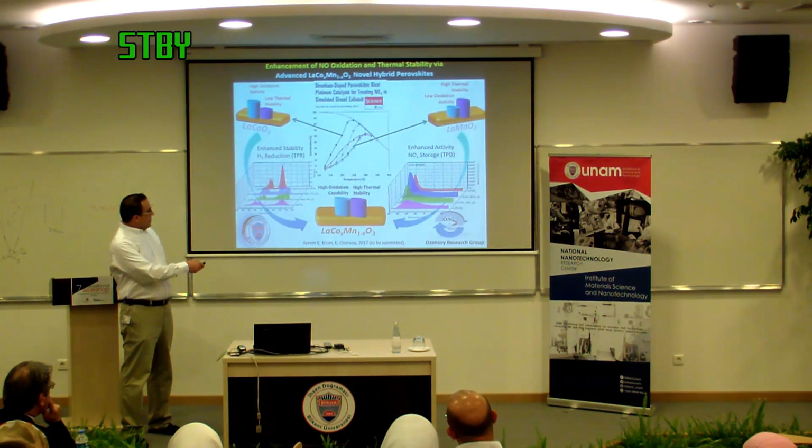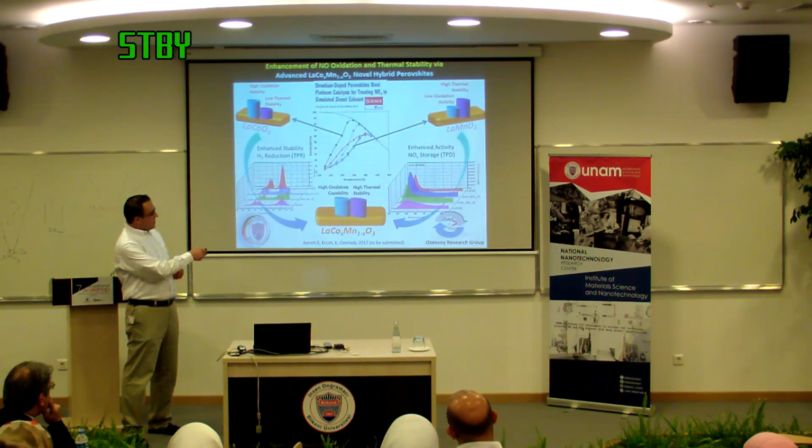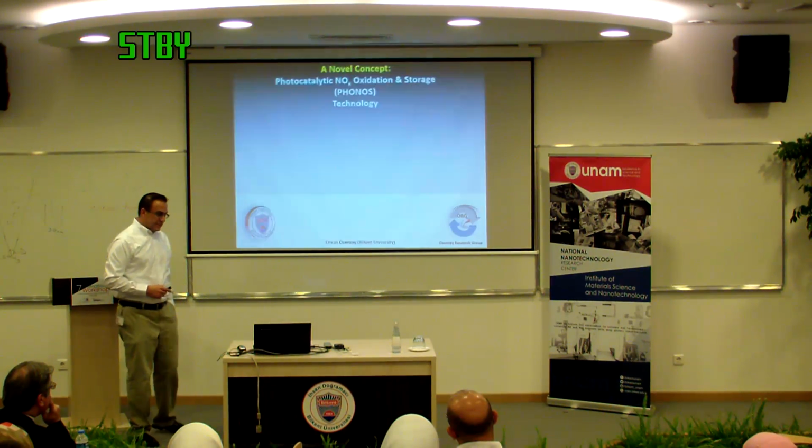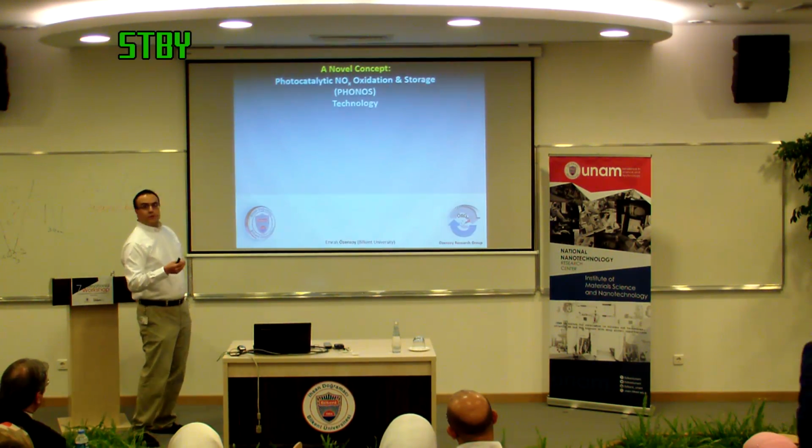So you can see that this particular material, with a cobalt to manganese ratio of 0.8 to 0.2, has a significantly higher oxidation capability, which is much better than anything published. So this was worked on with General Motors in the past. So these are all thermal processes.